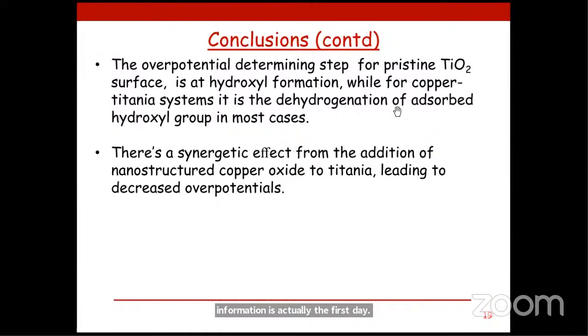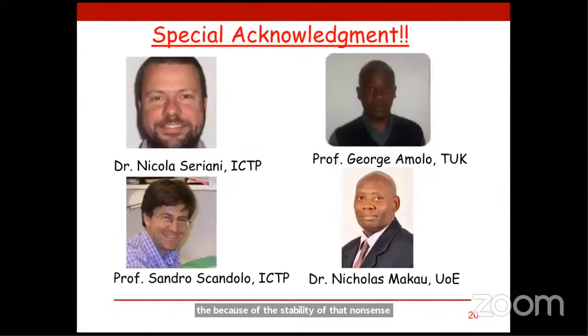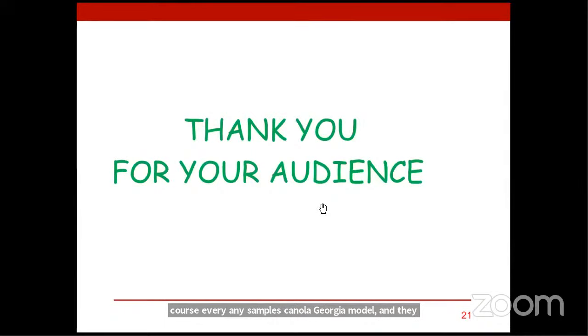Then lastly, there is a synergetic effect from the addition of the nanostructured copper oxide to titania, and this contributes to the reduction in the overpotential. And you can actually see that the most stable species under the effective bias is where the absorption takes place between the copper oxide nanowire and the TiO2. So that cooperative behavior contributes to the stability and the reduction of the potential. The stability I've talked about is because of the stability of the hydroxyl species. So I want to just acknowledge my co-authors, Nicola Seriani, Sandro Scandolo, George Amolo, and Nicholas Makau. Thank you to the audience.